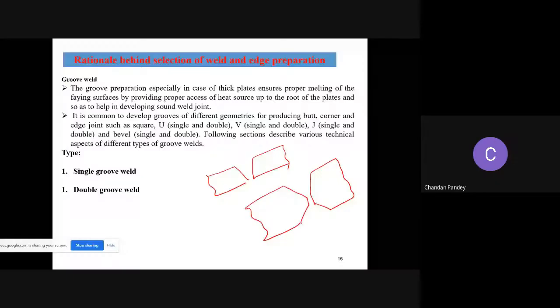Now, single groove weld is mainly used for plates of thickness more than 5 and less than 15 mm. Less than 5, then it is okay; we can join just by application of heat. And up to 15 mm, we can use single groove weld. Moreover, this limit is not hard and fast, and it depends upon the penetration capability of the welding process. We also consider the distortion that comes during welding, meaning the plate gets distorted due to the application of heat, and you get angular distortion like this. So we also consider distortion and residual stress in the welded joint, and on that basis we select the single groove weld for plates generally up to a thickness of 15 mm.